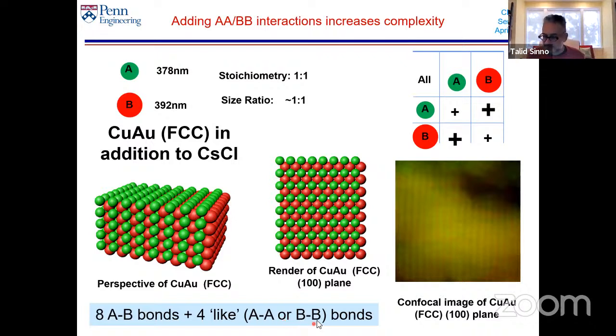So, very simply to understand this, the extra AA and BB interactions offered by this mixing is what favors this structure. It's more densely packed, which is entropically not favorable, but it's enthalpically favored by the additional interactions that we have. Okay, and so that's why this forms under these conditions.